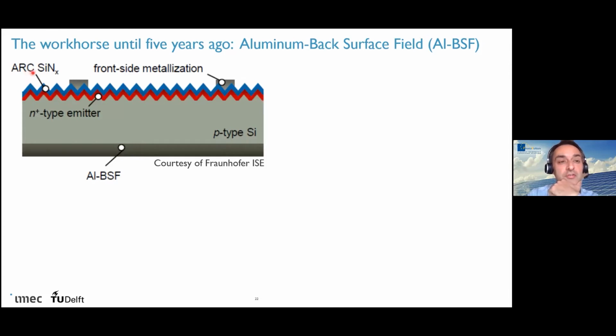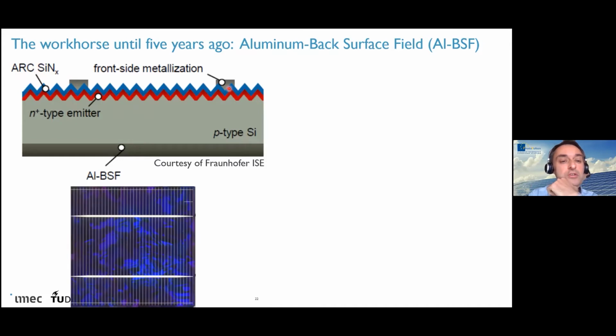You have at the front a silicon nitride layer that gives the blue color to the solar cell, so that acts as an anti-reflection coating and a passivation layer. And then at the front, you have metallization. You have these fingers, typically consisting of silver.